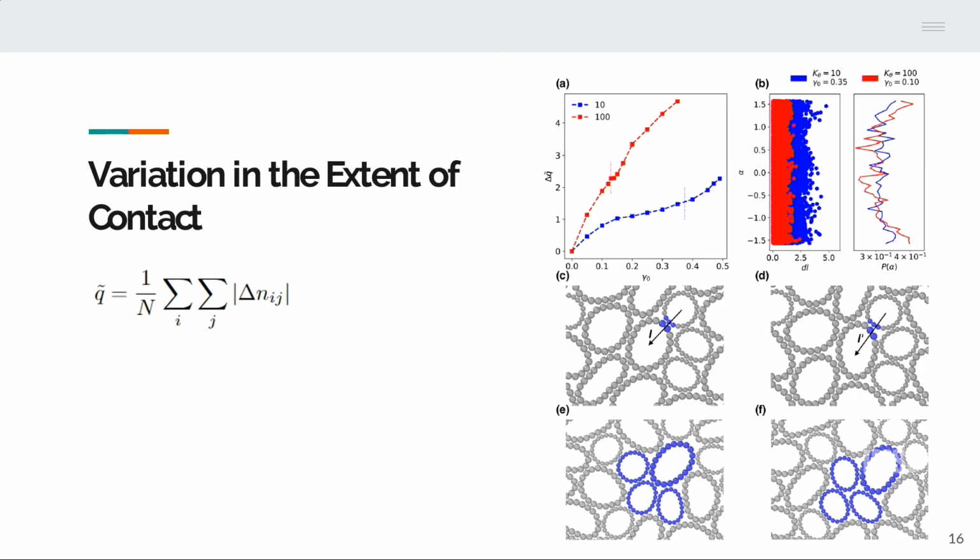but the increase is less for the more flexible rings, which kind of means that the more flexible rings are stickier. And we see this increase happens both below the threshold and above the threshold, so both in the elastic and plastic regime. And in the elastic regime, this is due to this kind of sliding motion, which is shown in the middle panel.